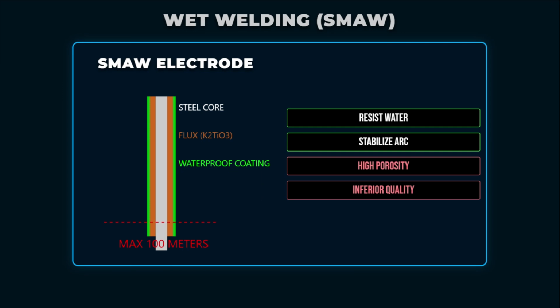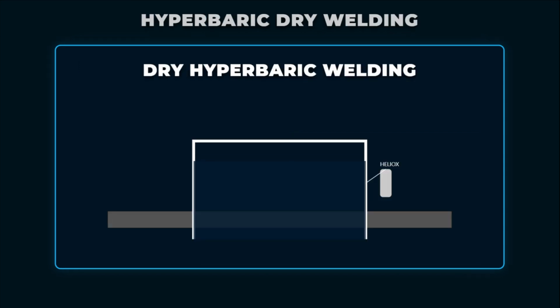Wet welding predominantly utilizes the shielded metal arc welding process, requiring specialized waterproof electrodes with potassium titanate flux coatings. These coatings are designed to stabilize the arc and minimize hydrogen pickup. The electrode coating must be highly resistant to water penetration to prevent short circuits and maintain flux integrity. Despite these specialized materials, the resulting weld quality is inherently inferior to surface welds due to the rapid cooling and porosity issues. American Welding Society standards typically restrict wet welds to depths within 100 meters and mandate specific mechanical testing protocols to verify minimum tensile strength and ductility requirements.